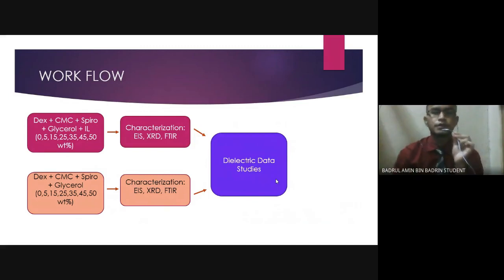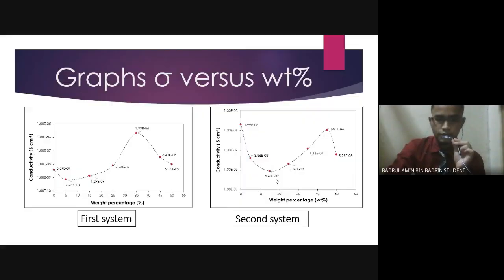So this is the first characterization, which is electrical impedance spectroscopy. We observe the sigma, which represents ionic conductivity, versus weight percentage. As you can see from the left graph, the highest sample is 35 weight percentage with ionic conductivity 1.99 to the power of -6.